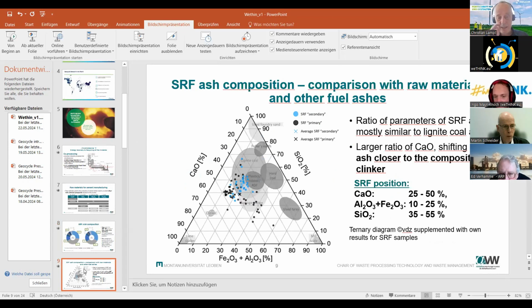Here you can see again this comparison. This is the composition of clinker, and the black points are the ash compositions of different main burner fuels, and the blue one is the calciner fuel. And as you can see, we are coming with this ash from the fuels quite close to the clinker composition. As you can see here, you have calcium oxide, silica oxide, and as a base, iron and aluminum oxides.